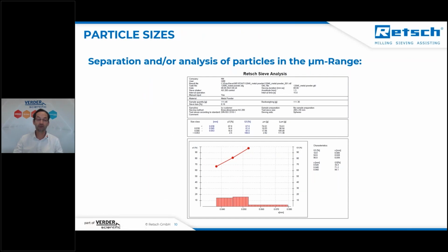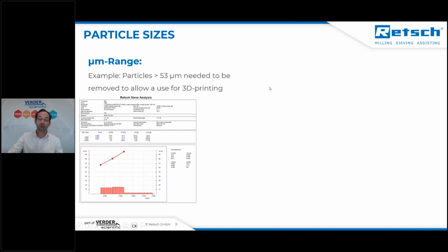So what does that mean? We've got a possibility to use sieves to separate particles. So either you separate these particles with a certain sieve size, but you also can completely analyze the particle size distribution of your sample. And here we are talking about the micrometer range. Here I show you just an example of the separation of a metal powder, where particles bigger than 53 micrometers had to be removed in order to allow the use of this fine powder for 3D printing.